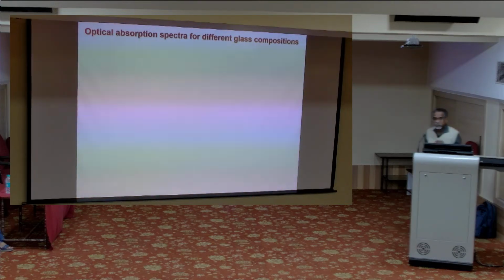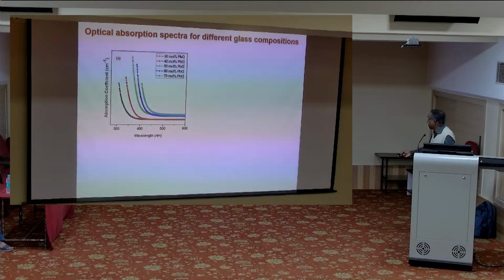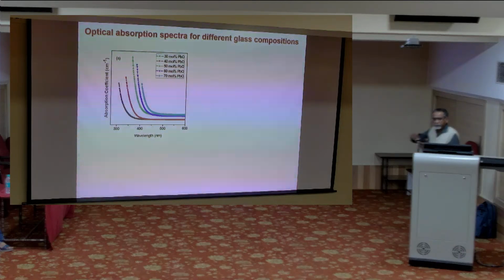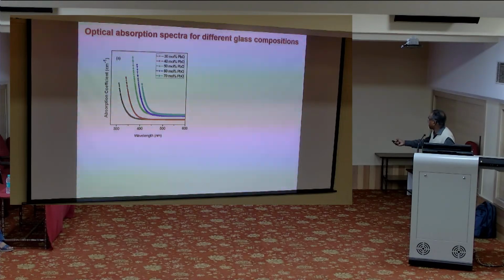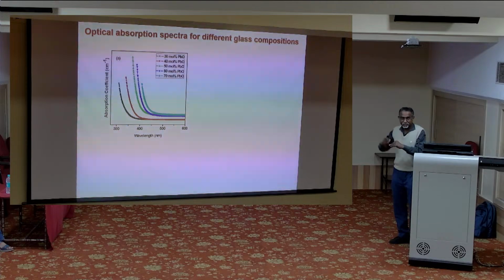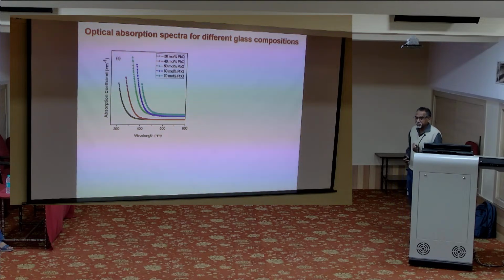So what happens to the optical absorption if you try to change the glass composition? What I showed was for a specific composition of the glass. So here, this is a series of lead borate glasses. Dr. Mallur showed you that, if you have 30 mole % of lead oxide, you keep varying the percentage of lead oxide in that glass. You can see that the optical absorption edge changes. As you go to higher and higher amount of lead, the glass absorption edge is shifting towards lower and lower energy. Higher energy means the gap is higher. Lower energy means the gap is getting smaller and smaller. So when you increase lead oxide, the optical absorption gap decreases as a function of glass composition.